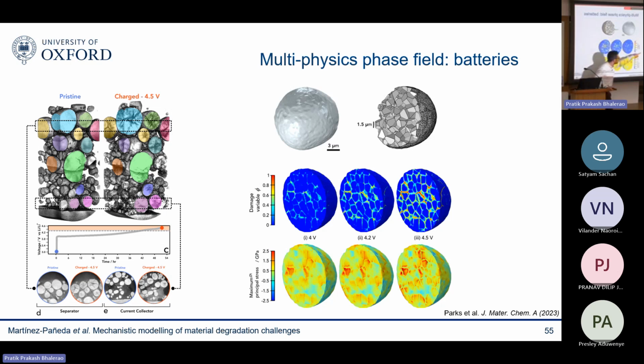So again, in combination with these very nice XCT facilities that they have, we can resolve that microstructure into the model. We can make the phase field grow only along the grain boundaries. You can distribute properties around, and we can do the simulations and predict what will be the evolution. And then we can play games. We can see what is the difference to having a single crystal. We can also change the microstructure. Maybe you have a graded microstructure where grains are smaller on the outer side, bigger in the inner side. All of those things you can do quickly with this type of models.